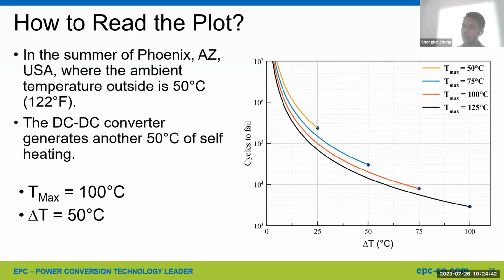Now let's come back to the plot on the right, where we can follow the orange curve, where Tmax is 100 Celsius. Then let's read from the horizontal axis with delta T of 50 Celsius, which is right here. Now we can read on the vertical axis, which is cycles to failure, about 20,000 cycles with 100 ppm failure rate. This just gives you an example of how to use our reliability testing result, test to fail, to walk you through a real world application lifetime estimation.